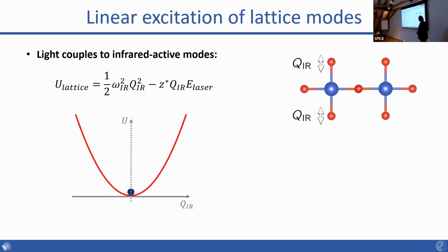And in this case, what happens when you drive the system with an electric field? We know that we can model phonons, the atoms in the material, as a series of balls and springs. So we have harmonic oscillators, and so we can write down the energy of this system as just a single harmonic oscillator corresponding to the energy of this mode. And this is an infrared active mode, so it's going to couple linearly to the electric field of our laser pulse, right? So in this case, I'm going to send the laser onto my sample.